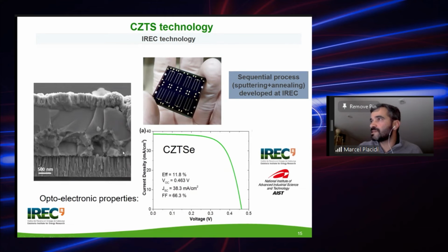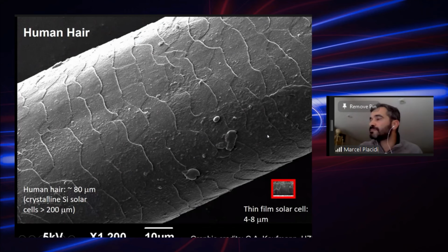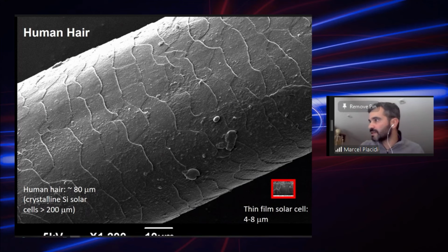And here in this figure, we can see an image of a sample with several solar cells with anti-reflective coating. In fact, this sample was the best we fabricated at IREC, and it was giving an efficiency of close to 12%, as we can see there in this current-voltage characteristic. This figure is just to show that finally the active area of this solar cell is very small. It's something less than 5 microns, as we can see there. And it's quite amazing if we compare, for example, with a human hair, that energy can be produced from such a small area, no?